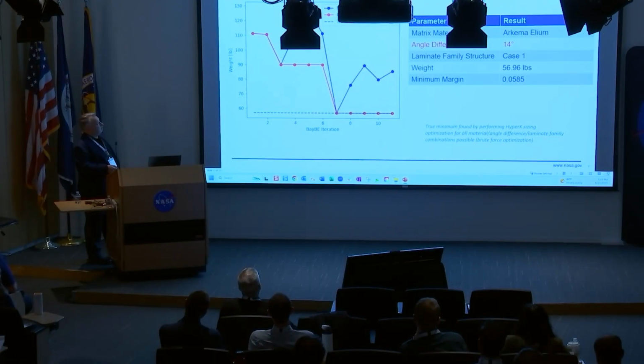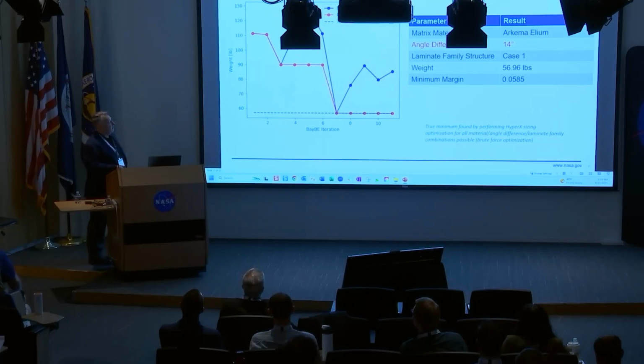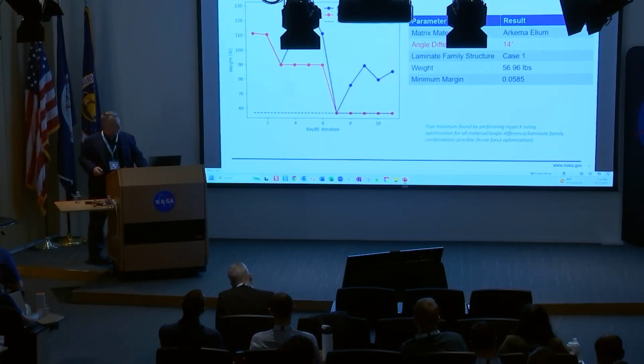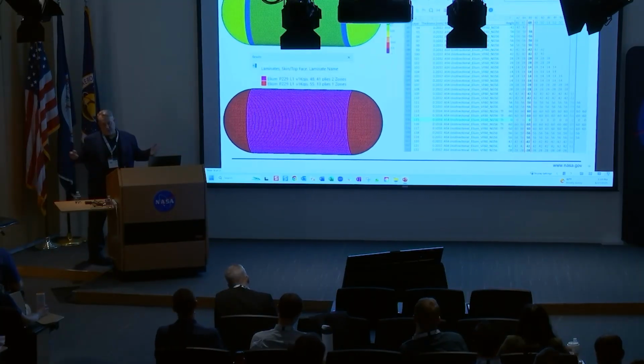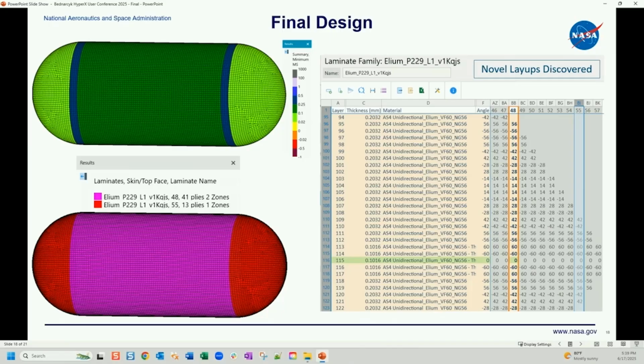So the matrix material was this Arkema thermoplastic. The angle steps between those pairs was 14 degrees. Among those 4 cases, it actually used case 1. There's the weight, and the minimum margin was 0.0585. So at the end of this, we have a closed design in HyperX that was totally generated by this scripting.